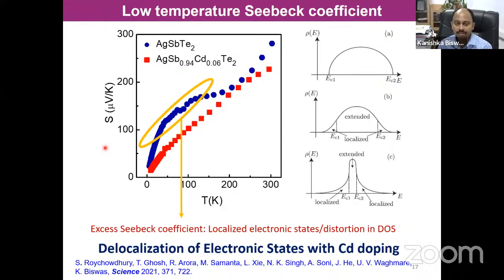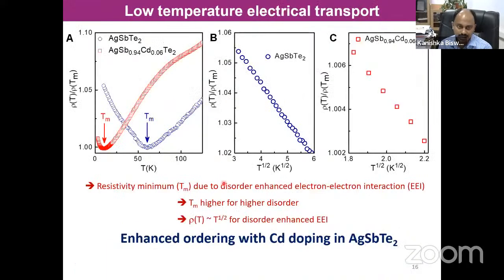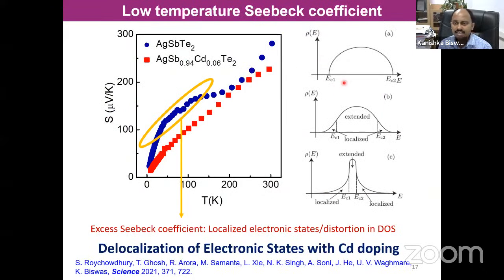In the low temperature Seebeck coefficient, you see like this pristine sample, I have a bump in the Seebeck coefficient exactly at the same temperature where this minima comes. And this bump is nothing but the distortion of the density of states, as Mott predicted a long time back. We see a jump in the Seebeck coefficient. As soon as I dope cadmium, the bump goes away. So that means the mobility edge is going far away from the Fermi level. So we have a delocalization of the electron states due to partial ordering of silver and antimony.